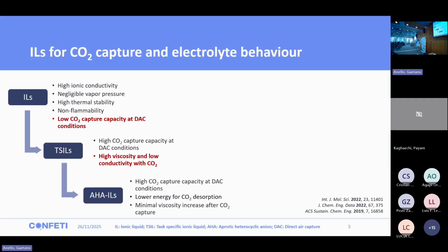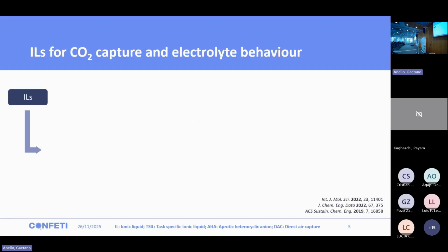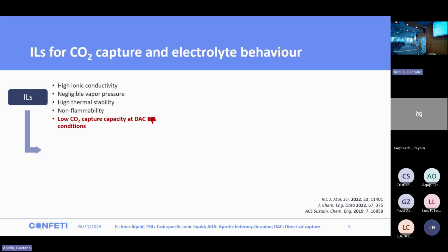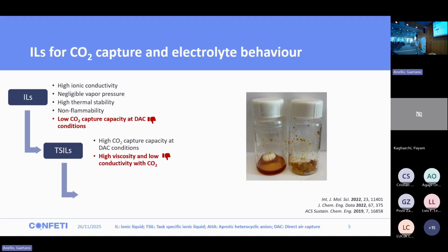But let me explain why ionic liquids are particularly interesting for this application. Commercial ionic liquids have excellent properties like high ionic conductivity, negligible vapor pressure, high thermal stability, and they are non-flammable. However, they have a critical limitation: low CO2 capture at direct air capture conditions. So here is where task-specific ionic liquids appear. These ionic liquids have a high CO2 capture capacity because they are specifically designed to bind chemically the CO2. However, the drawback of this material is that when they capture the CO2, the viscosity increases dramatically, as you can see in this image, and they become solids.